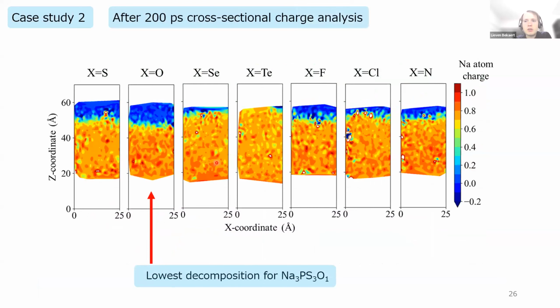And here is another way of visualizing it. So in blue, we have the sodium metal. So we visualize here the sodium atom charge cross-sectionally. And you can see that for oxygen, the majority of sodium remains, followed by sulfur and then by the other elements. Now we were able to confirm that this is because of chemical properties. For example, oxygen is in the same group as sulfur. It's smaller than sulfur. The valency is also the same. For example, if you look at other elements such as fluorine and chlorine, larger in the case of chlorine, but fluorine it's smaller. However, you have a different valency, so that causes instabilities in the structure of these PS4 groups. So that's why using oxygen, also from a theoretical point of view, gave the best results.